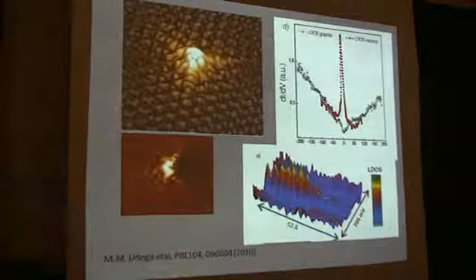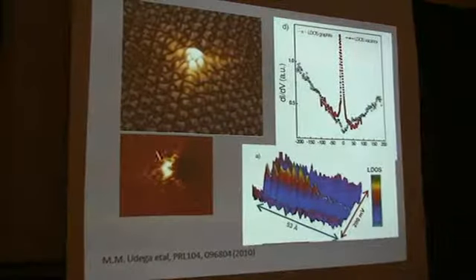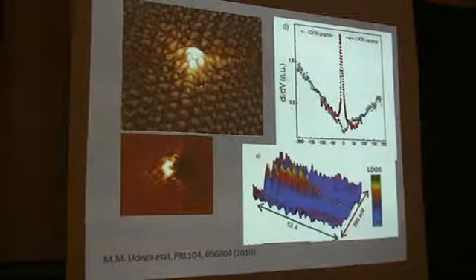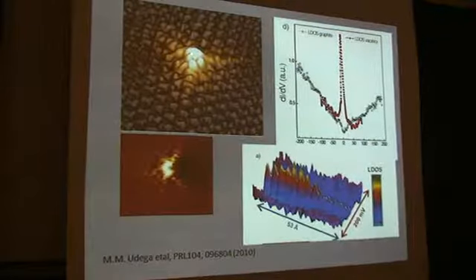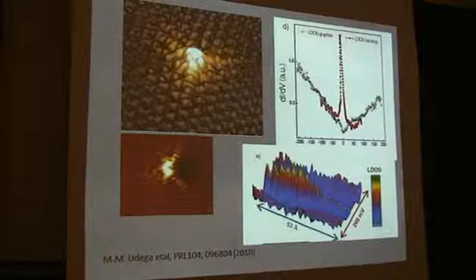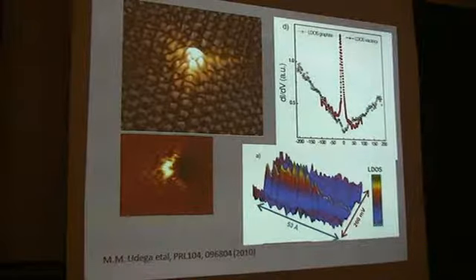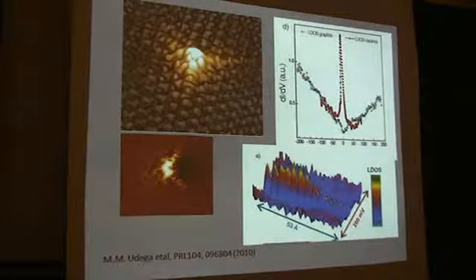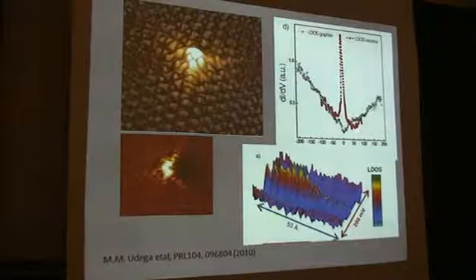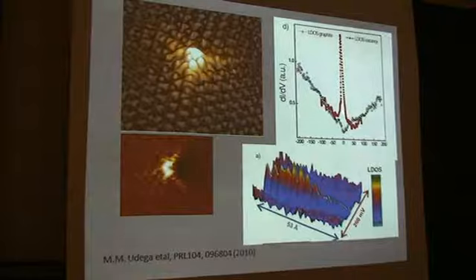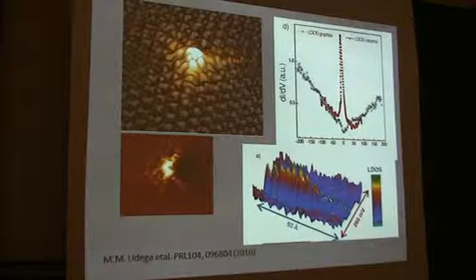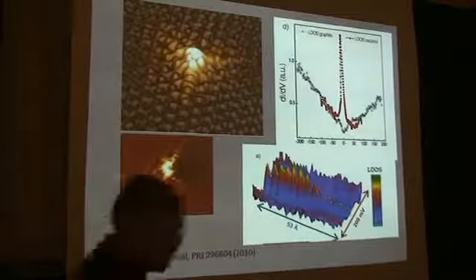Now, it happened actually, it took them a while, but they looked at this in a PRL published in March of last year, 2010, where they looked at irradiated graphene and knocked off one carbon atom with ion radiation. And what they produce is, you can see inside this V shape, if you tunnel away from the impurity site or defect site, you have this sharp resonance. And if you go along this ridge, which is shown here, you do have this beating with the right wave vector, but on top of it you have the overall envelope that goes like 1 over R squared in the tunneling conductance.